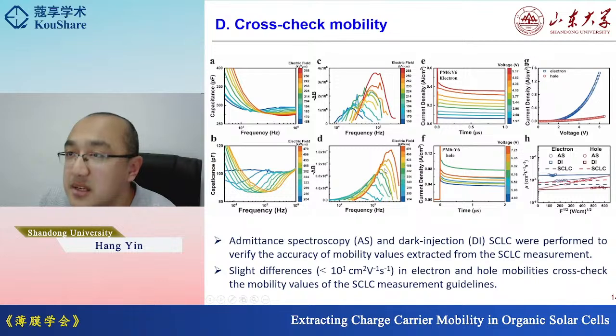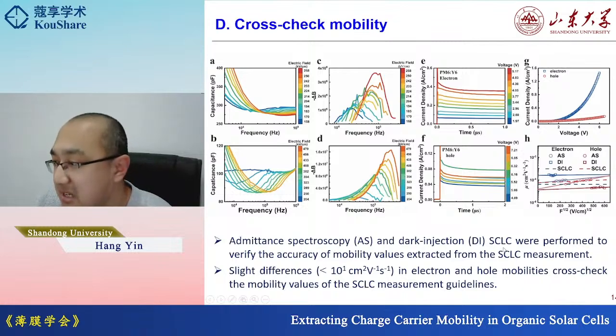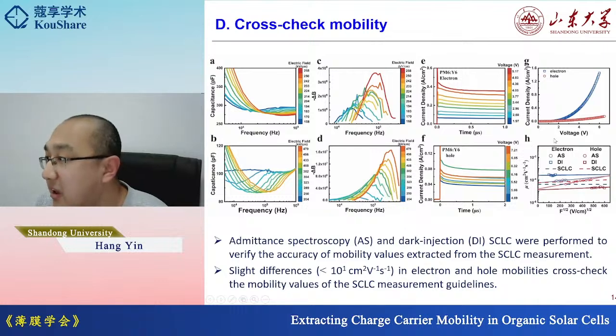And then we cross-check the mobility values by different techniques. We just used the admittance spectroscopy technique and the dark injection space-charge-limited current. We just performed them to verify the accuracy of the mobility values. And we can see the figure H, right? If we use the right model, for different techniques, we can get very close zero-field electron and hole mobilities, which means that after the cross-check with different techniques, we can confirm the selection of the fitting models of the SCLC should be right, or relatively right.